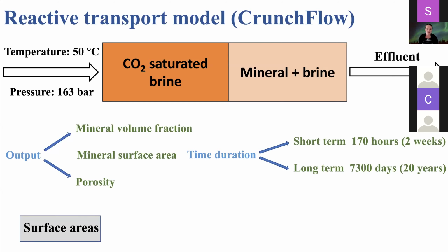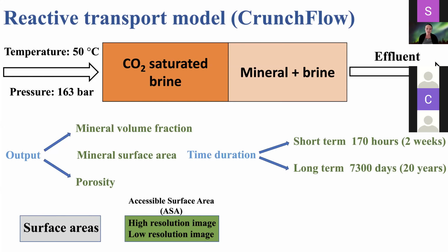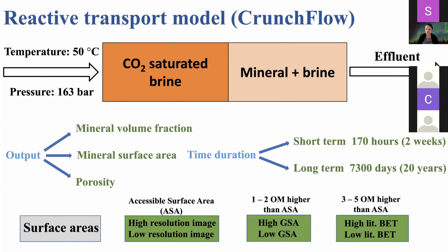In terms of surface areas, we're going to build simulations using our accessible surface areas obtained from the lowest and highest resolution images, as well as look at what if we had used surface areas from those other approaches. So from a geometric surface area, which are typically 1 to 2 orders of magnitude higher than the accessible surface area, and then the BET surface area values, which are even higher than the accessible surface areas.